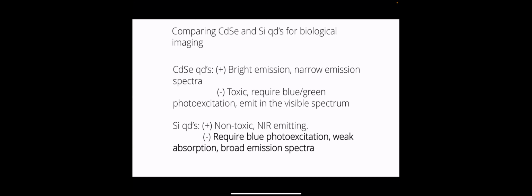But the one drawback with silicon is that its light absorption near the band edge is really weak. Silicon's an indirect band gap semiconductor, so its absorption coefficient is really low near the band edge. So the emission can be, say, 800 nanometers, but the light absorption is actually really weak there. And so usually when we do photoluminescence spectroscopy, emission spectroscopy, we'll photoexcite at about 400 nanometers. It's not because the material doesn't absorb out at 600 nanometers or so, but the density of states is low and the light absorption is weak.